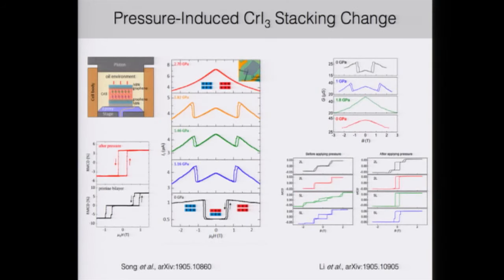There's also been work more recently on the arXiv by both Xiaodong Xu's group and Kin Fai Mak's group at Cornell on pressure-induced chromium iodide stacking change, where they take a bilayer chromium iodide magnetic tunnel junction and place it in a diamond anvil cell and apply pressure, and then they're able to irreversibly change the crystal from the antiferromagnetic coupling to the ferromagnetic coupling. So this is further evidence that we are really depending on stacking for these magnetic changes in the bulk to ultra-thin chromium trihalides.